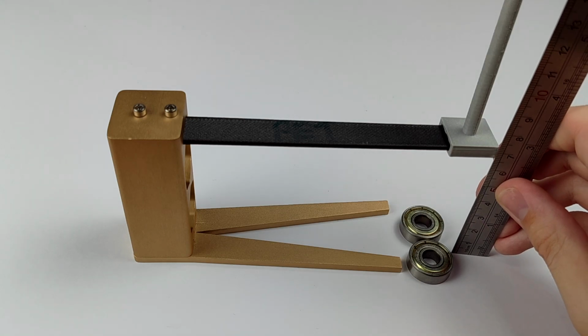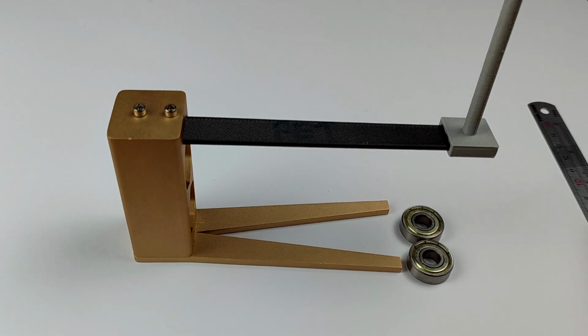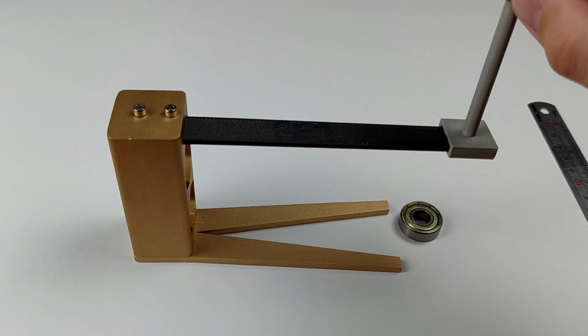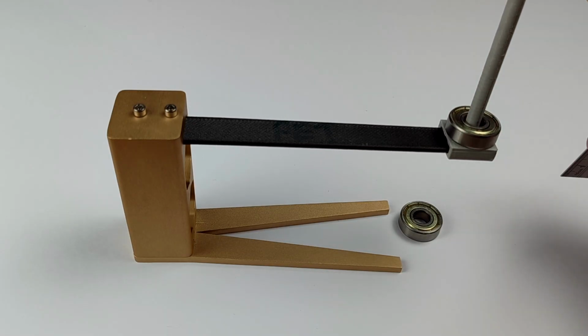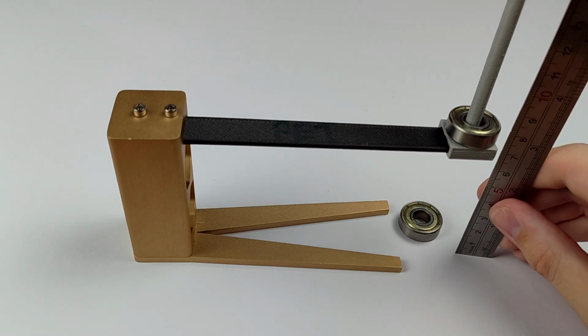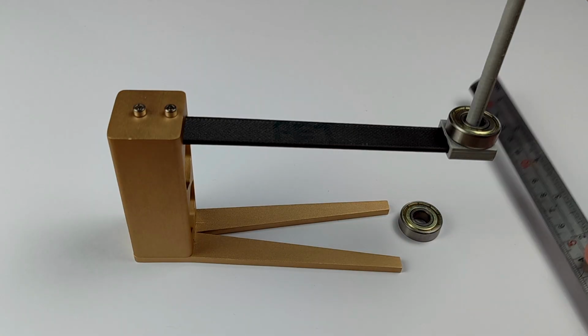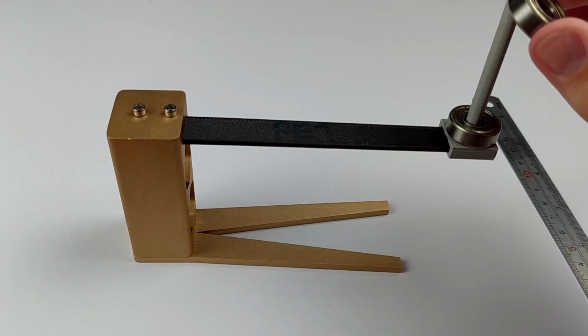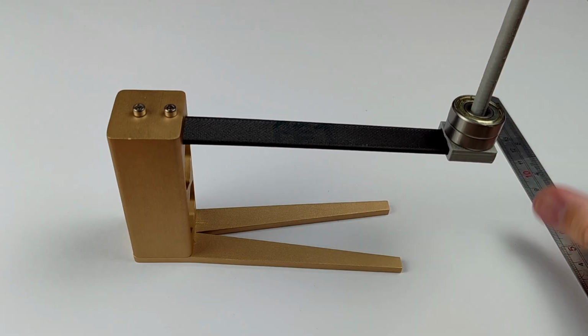Third, I add a small mass to the holder, and then measure the new position after it stopped moving. I'll repeat this, adding more weights and keep recording the deflection for each. Finally, I'll flip the strip and repeat everything. Taking an average of both orientations should help cancel out any directional biases.